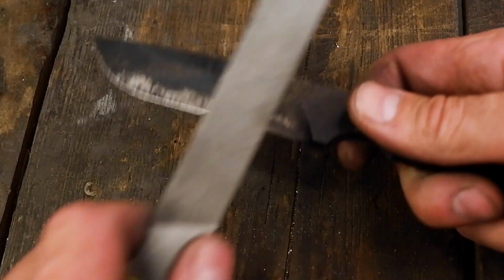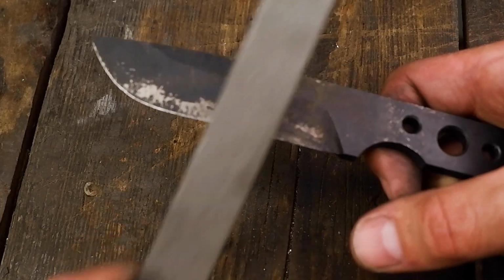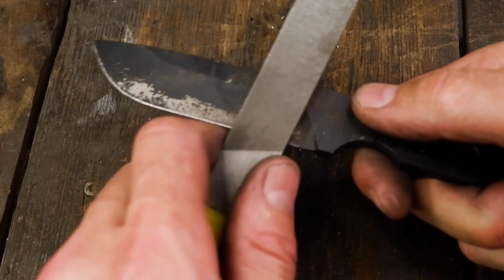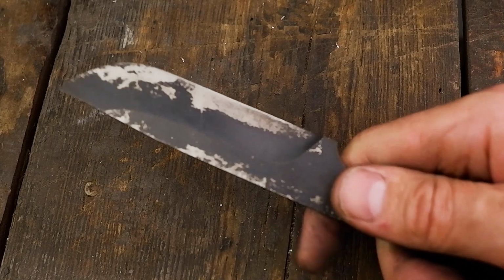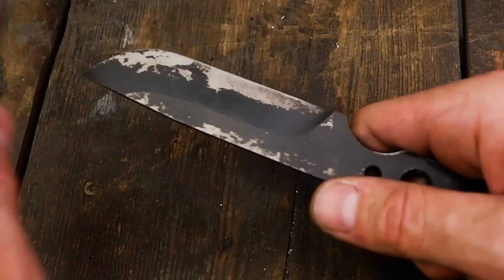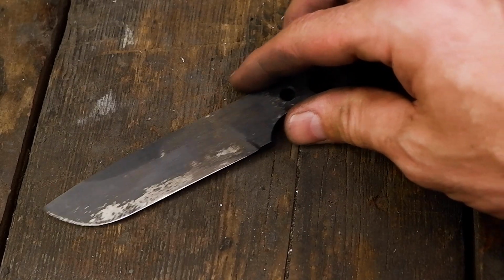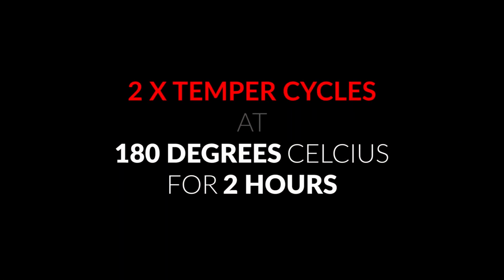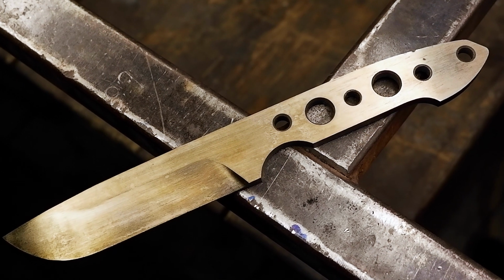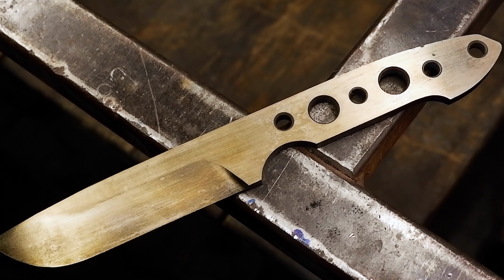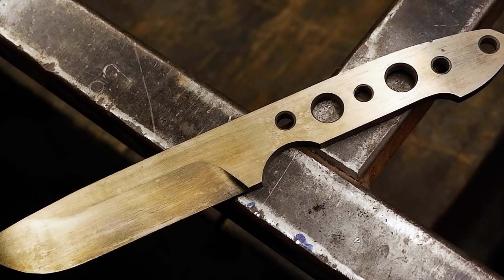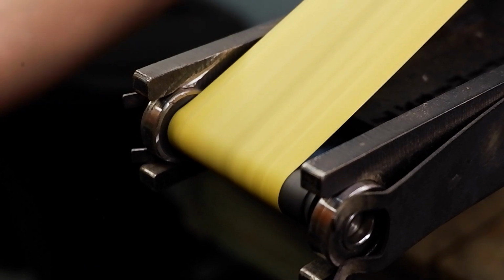To check that the steel hardened properly, run a file down the edge of the blade. If it skates off with that high-pitched glassy sound, your blade hardened. Proceed to the tempering process. After the tempering process, the blade should have a golden straw color tone to it. If you see any blue coloring, you might have over-tempered the blade.